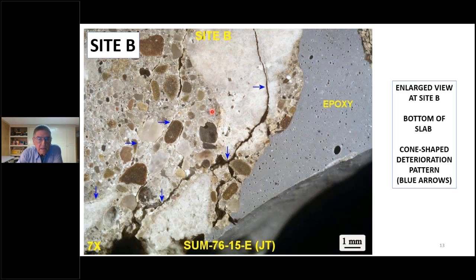And I will say that in all the 20 cores that we looked at from the joint areas, we saw this sort of thing to some degree in all of them. We didn't see it in all of the ones from the mid-slab cracks, but in all of the joints, this was the case. So there's no question that this is going on. It's very common, and these are pavements that were still rated as good performing at the time, and as far as I know, are still performing satisfactorily. But that's the situation.